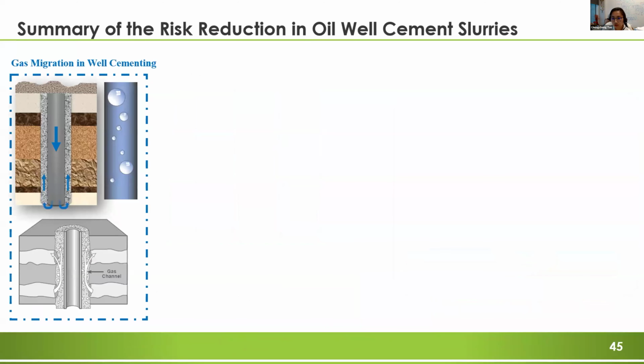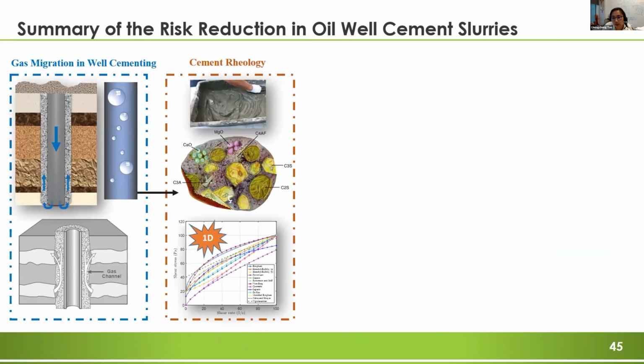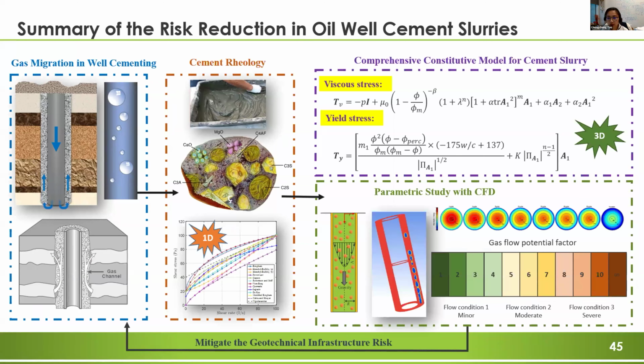So this is a summary of this research project. In conclusion, gas migration is a serious problem in well cementing. Understanding the rheology of oil well cement is very important for us to reduce the drilling risks in well cementing. After we reviewed the rheology models, we found that most of the models are one-dimensional and only consider single factors in the model. So we came up with a comprehensive rheological model for the oil well cement slurries in 3 dimensions, considering different factors like shear rate, volume fraction, water to cement ratio, thixotropic behavior, and so on.